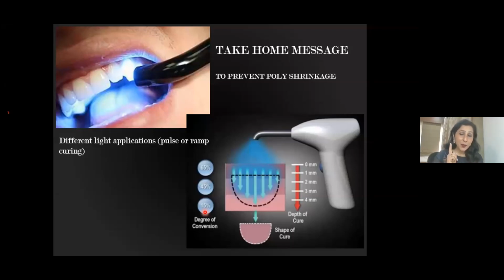And always remember to put your light cure probe perpendicular to the tooth surface. Do not put it tilted. Don't put it obliquely on the tooth surface, otherwise you will be at a loss. You will lead to polymerization stresses, you will lead to polymerization shrinkage at a wrong place.